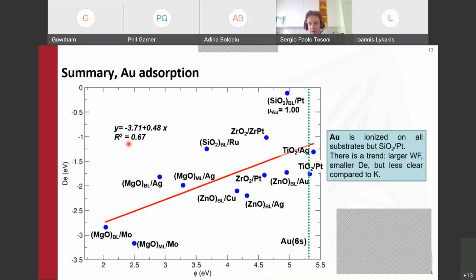So in the case of gold, we have some other factors like a covalent character of the bonding that starts to take place. And this is evident, for instance, in the case of the zinc oxide bilayer on silver or gold. As you can see, we have a larger adsorption energy than we could expect compared to a purely ionic trend. This is due to the fact that the orbitals of silver are pretty much protruding in space. The same holds true up to a certain extent for gold, and this induces a mix-up with the orbitals of gold and stabilizes the bond.